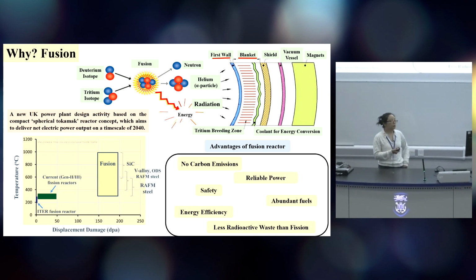So the UK announced it will build its own fusion reactor and aims to drive electricity power by 2040. And to build the fusion reactor, we face a challenge because fusion requires a harsh service environment, which especially challenges the materials design, because compared to fission it requires a wider range of service temperature, from 1000 degrees to 300, and also has extremely high displacement damage. And this especially challenges the first wall and the blanket, because the first wall and the blanket are the materials directly facing the irradiation, plasma, and extremely high temperature, and protect the external components.